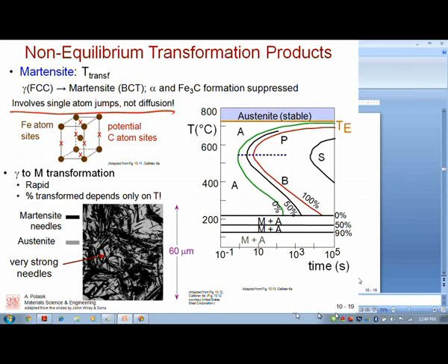It's much harder, right? Dislocations want to move along those close packed directions and planes, because then the actual movement of a line of broken bonds, or that extra plane of atoms, if you go back and look at how we look at dislocation motion in 3 dimensions, is much harder if I have to hop from here to the other side of the stage. Much bigger energy barrier. Dislocation slip is very, very, very difficult now in this body-centered tetragonal phase. Here's the weird thing about martensite. It's diffusionless, so the amount of martensite that forms is dependent only on the temperature.